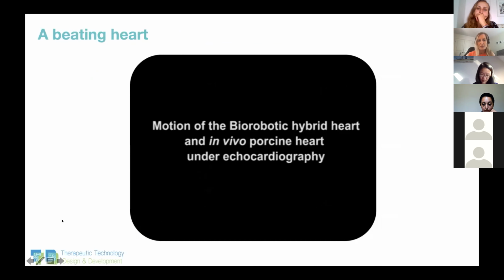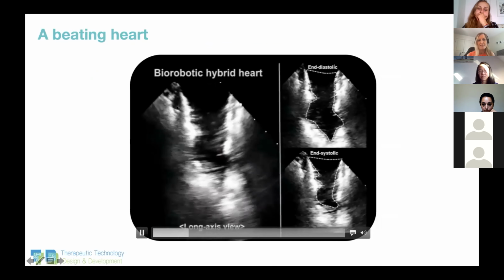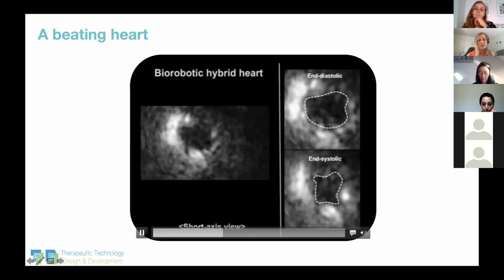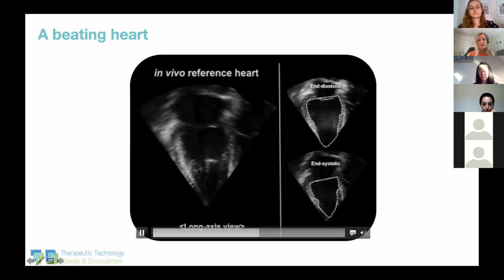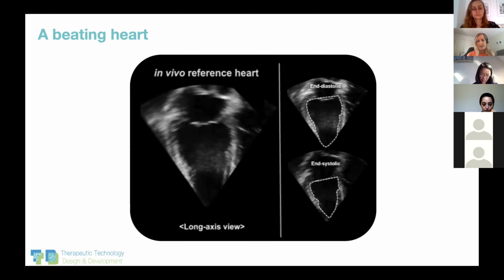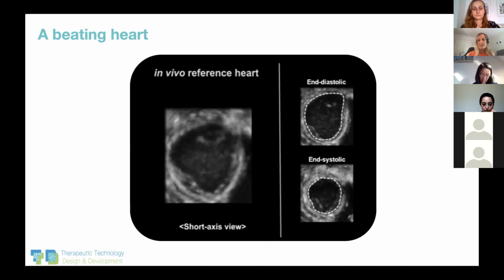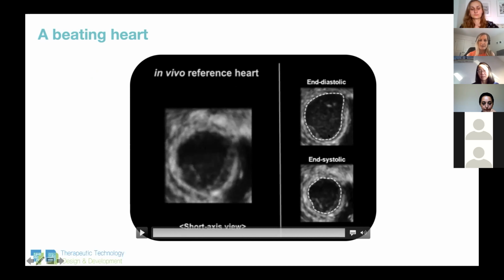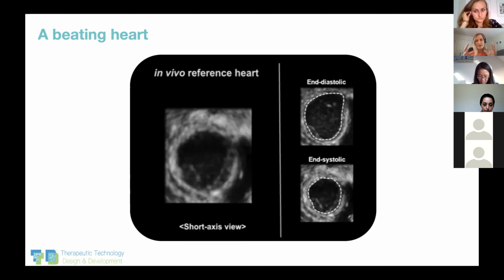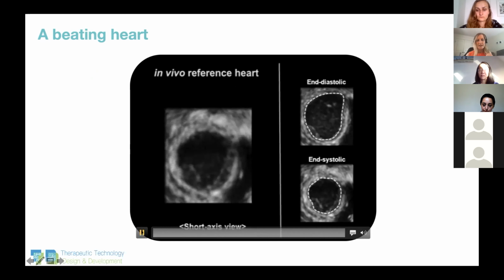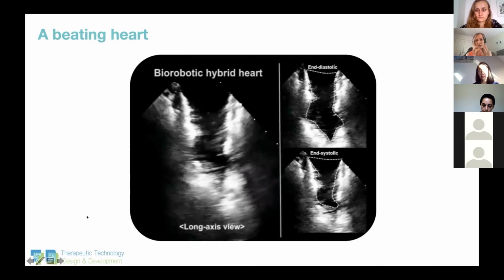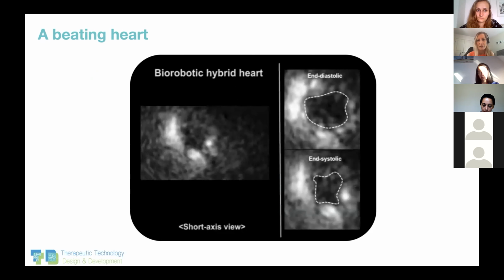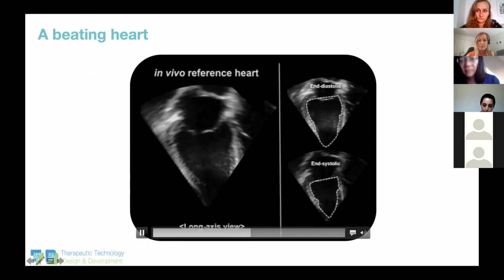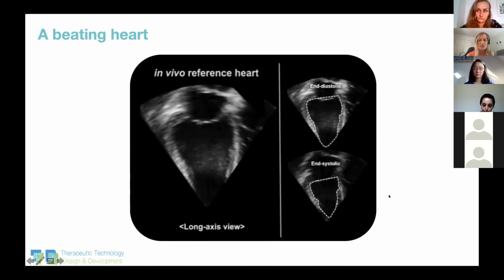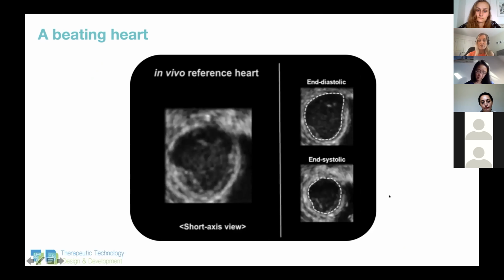Then we show the motion here. So when we pressurize these, we get motion of the left ventricle. So this shows the left ventricle moving under echo and from a cross-sectional view. And this is reference of an actual heart. So you can see from end diastolic to end systolic, which is the end of the relaxation period of the heart to the end of the contraction period of the heart, you get this contraction of the ventricle. And if I play that again, we see similar contraction of the ventricle in the biorobotic hybrid heart. And we saw similar percentages of contraction with the robotic heart compared to the reference heart.